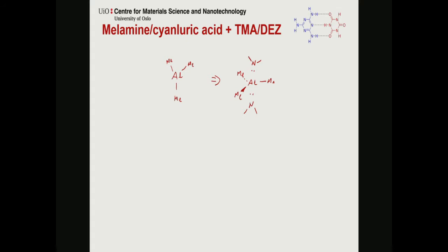Trimethyl aluminium is this aluminium with 3 methyl groups. In a precursor when you start, it is actually a dimer, but at some point it's converted into a monomer. And as a dimer, it's tetrahedrally coordinated. But this here really would like some electrons. So we could coordinate it into these nitrogens here and make, in principle, a structure. And I think it was Steven George that showed that you could make this with a trimethyl aluminium, and you can make a nice stable film until you took it out of the reactor. So these are also highly reactive.